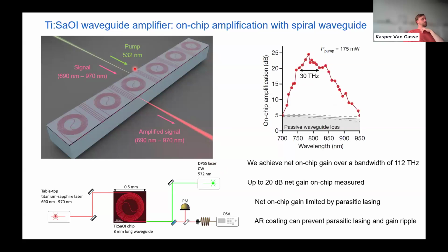So instead of using this short straight waveguide, we now use the spiral. We pump that with a tabletop solid state laser to get a quite strong inversion. And then we amplify, I don't know, 100 microwatts output from our tabletop tunable titanium sapphire laser. And what we see is that we can get up to 20 dB of net gain. And again, that we have an extremely wide gain bandwidth.